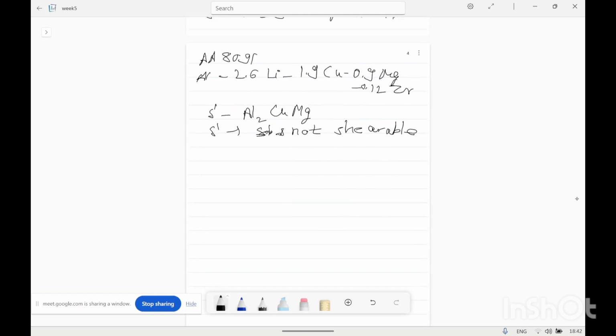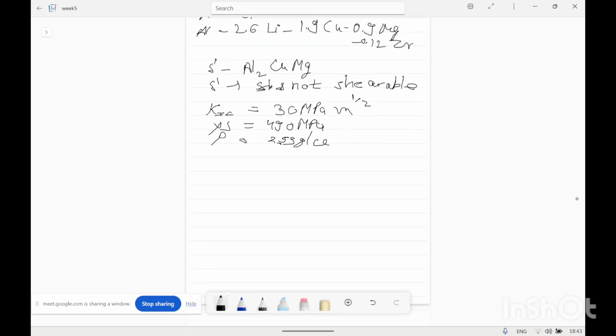So in the 8091 alloy, the S prime precipitate is not shearable, so the strength is a little high, but the fracture toughness could not be increased much as compared to the previous alloys. So this has a fracture toughness KIC value of 30 MPa root meter and a yield strength of 490 MPa, with a density of 2.5 gram per cc. The fracture toughness is very low while the yield strength is very high.